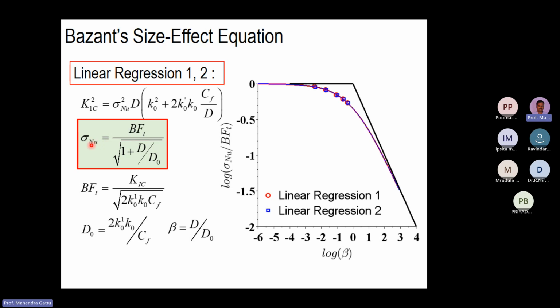So we have sigma N by B f_t here, and we're taking a logarithm of that, plotting it here. And we have log of D by D naught here, that is plotted here. From the FEM solution, we have sigma N by B f_t, which is sketched here. All the data points are sketched here. So we are seeing that as the size of the structure